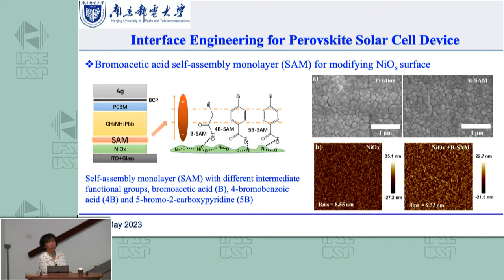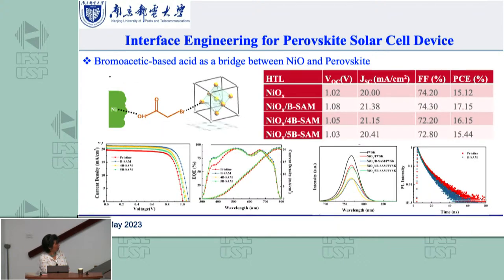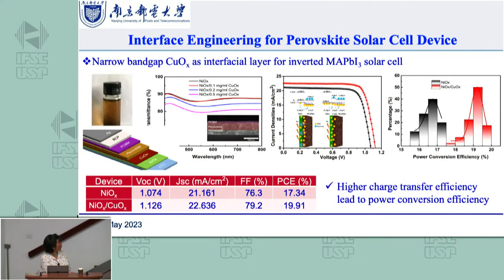So we use the inverted structure. After ITO, we make the nickel oxide and add something between the perovskite and the nickel oxide, that's SAM, a long name like that. That can make the film smoother to reduce the defects and then increase the efficiency. So that is one work we have done. Another thing is we use copper oxide, putting it between the nickel oxide and the perovskite. It can also reduce the defects and increase the efficiency.